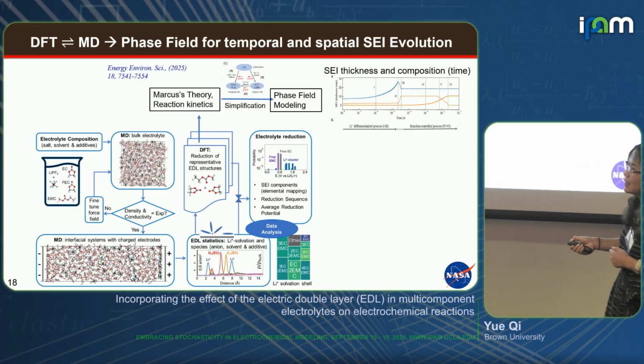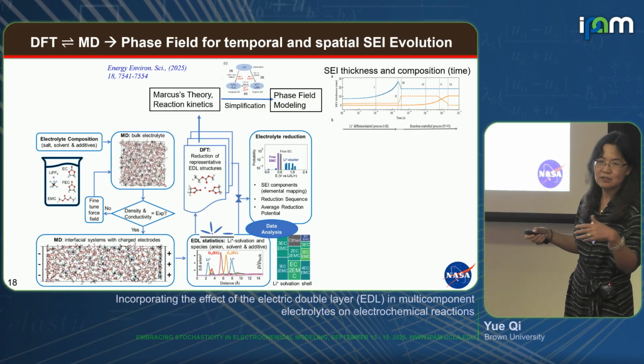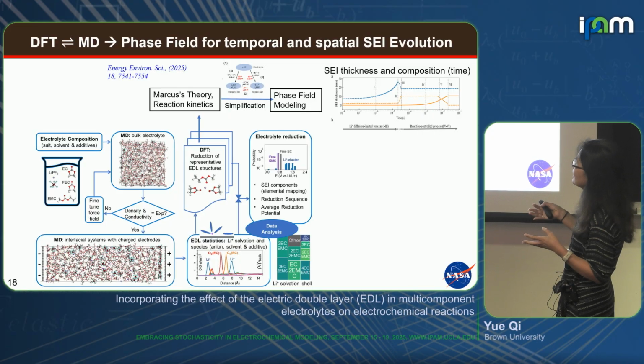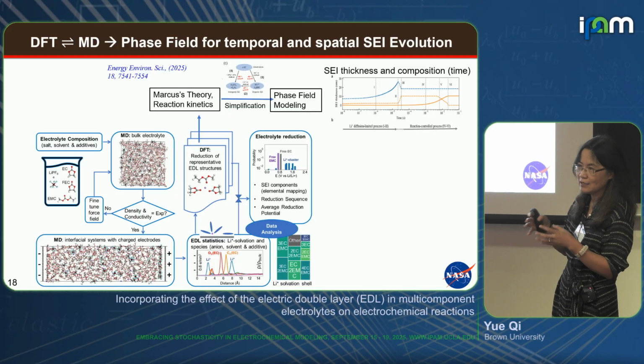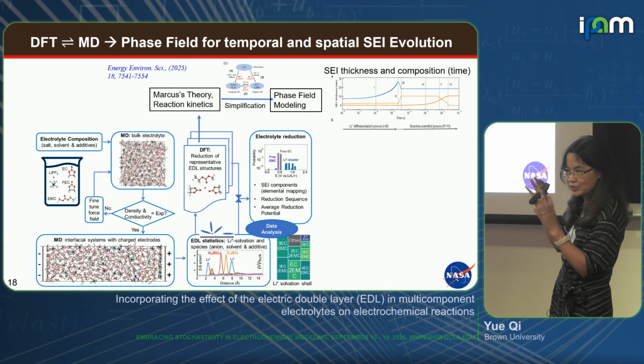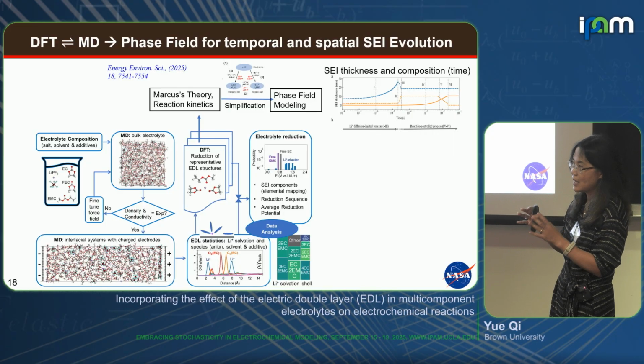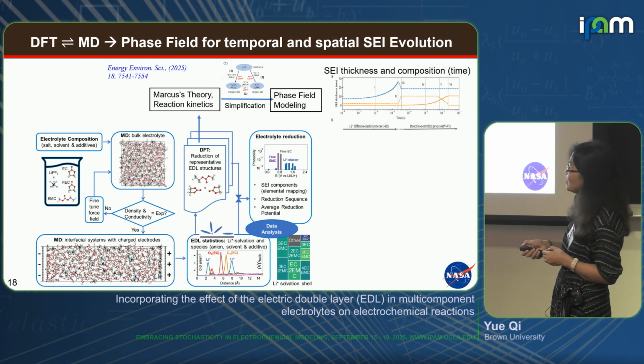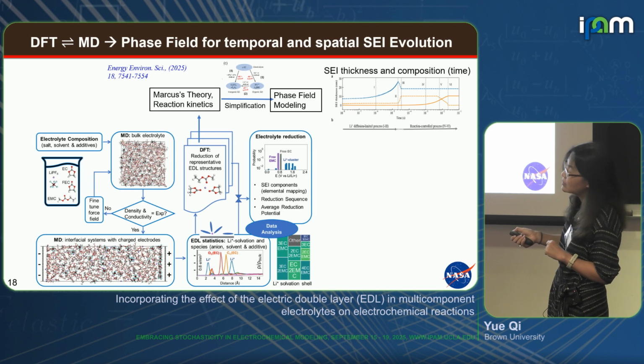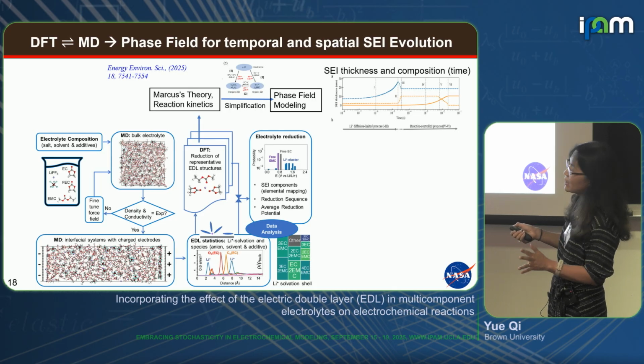So we have a pot. Remember the 32 EC molecules I had before? I did tight binding calculations. That's actually a fake electrolyte, and EC is not even a liquid at room temperature. It has to be mixed with something, a co-solvent, to make it liquid, and it also becomes liquid when it dissolves salt. And so we want to model the real electrolyte, the real composition.